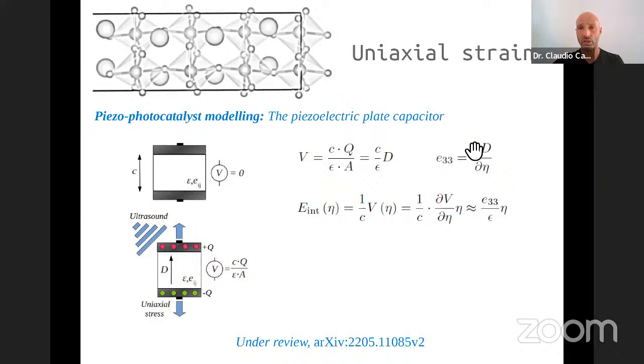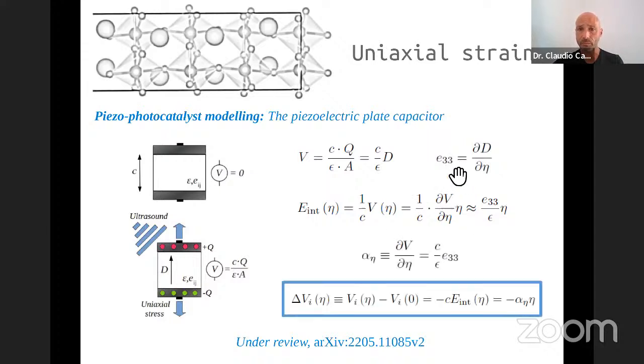then, based on this definition of the piezoelectric coefficient, the internal electric field is proportional to this piezoelectric coefficient. At the same time, based on this expression, we can define this new piezoelectric coefficient, which simply tells us how this potential drop changes as a function of the uniaxial strain applied in this direction. And it gets something as simple as that. Again, it's a huge simplification, but we do this because we are going to use this simple model in order to make a high-throughput screening of materials.